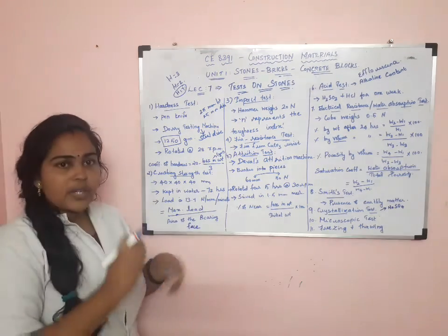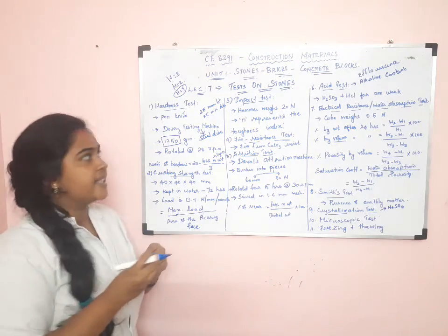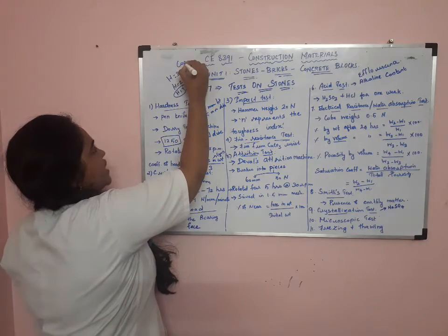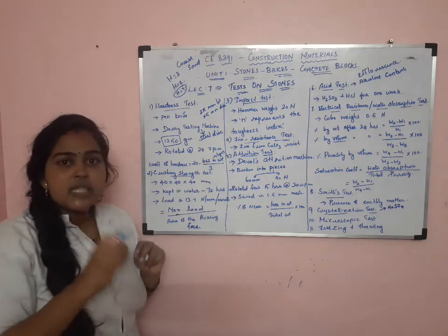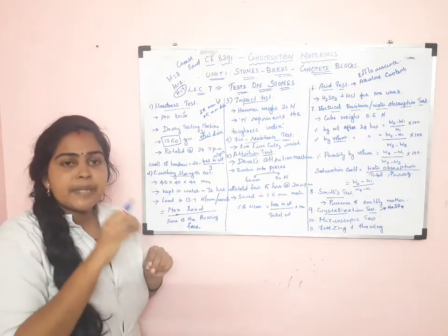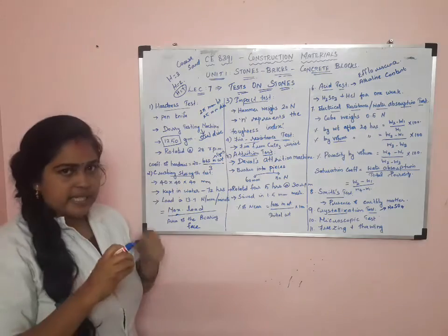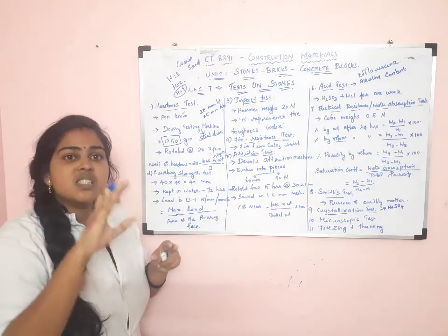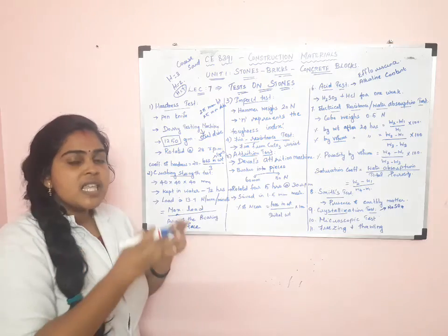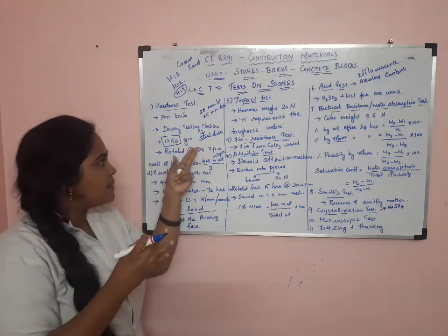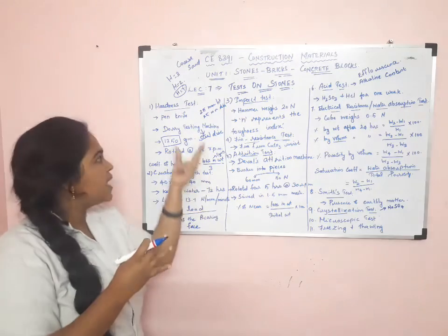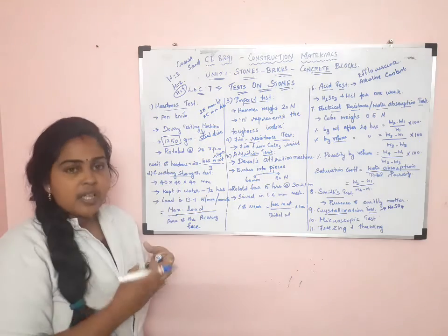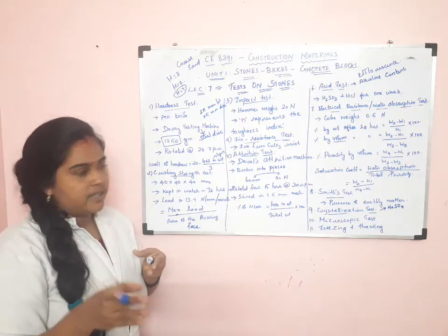While rotating, coarse sand, not fine sand, of standard specification is sprinkled on the steel disc. After 1000 revolutions, the sample stone is taken out from the Dorry testing machine and the weight is taken.